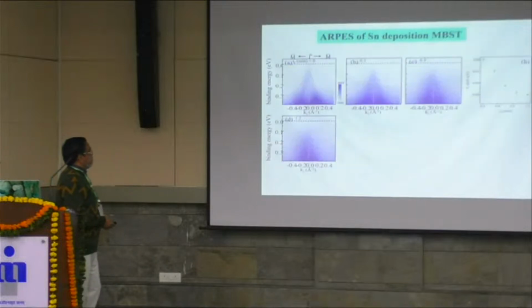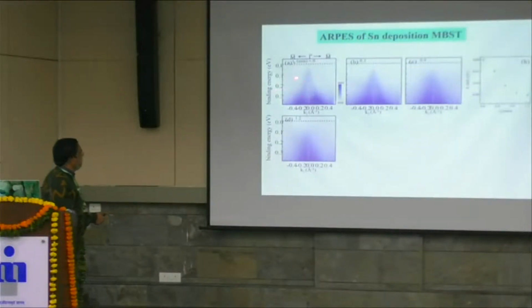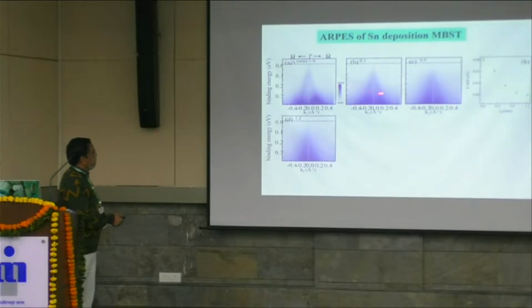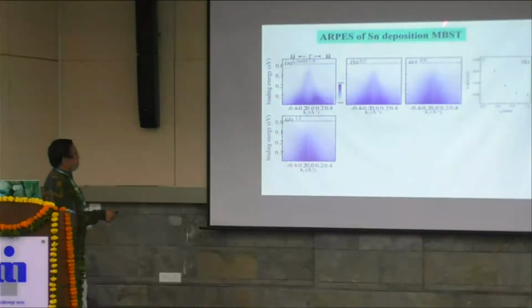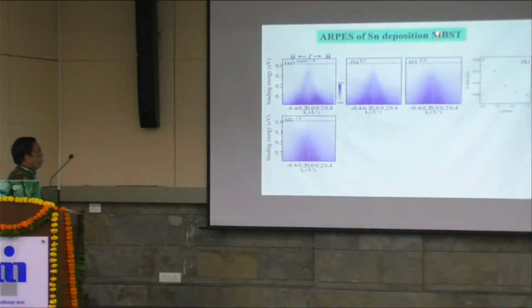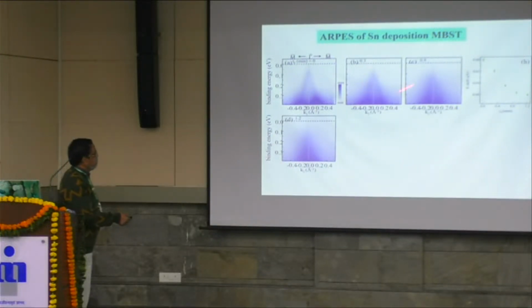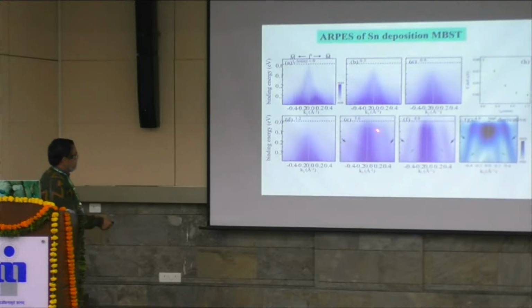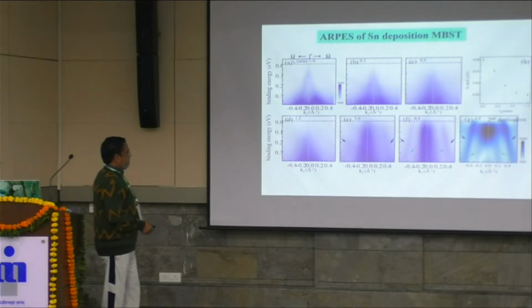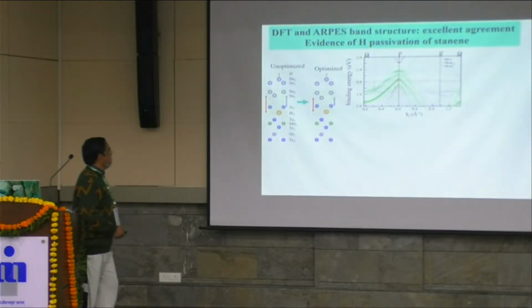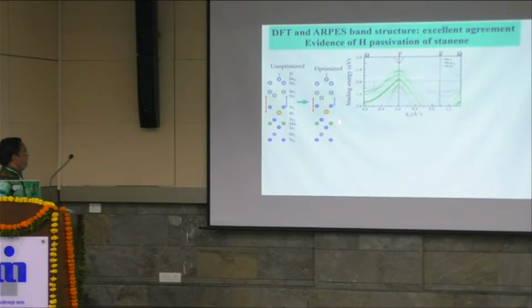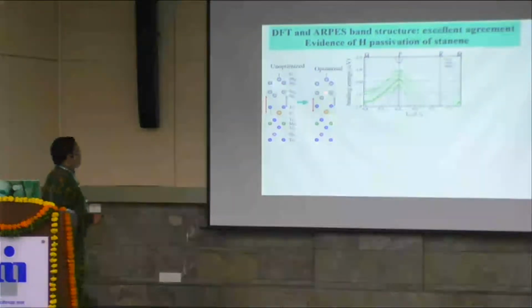And then we also look at ARPES. So these are the different ARPES bands. This is with no tin deposited, as in deposit time zero. These are the bulk bands of MBST, Sb-doped MnBi2Te4, and it goes down, and at this deposition time, 3.6 minutes, you start seeing the stanene bands. Now these stanene bands, to establish that they are stanene bands, we have done DFT, and DFT plays a very important role here.